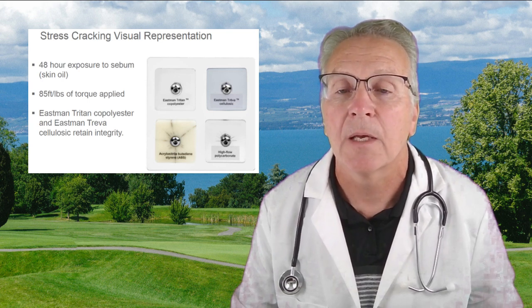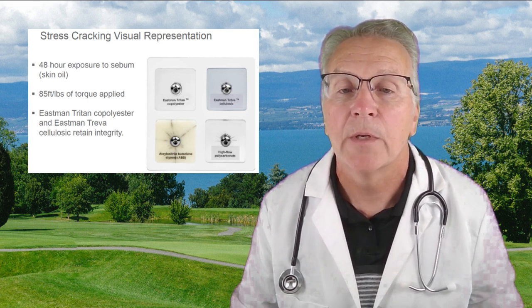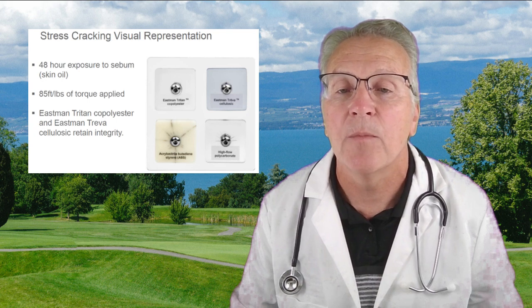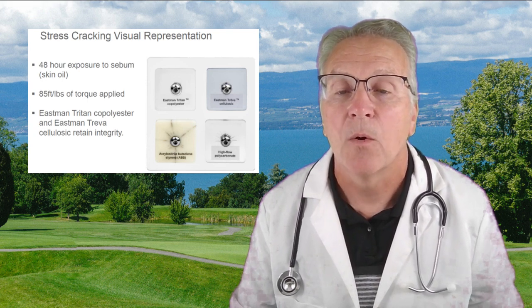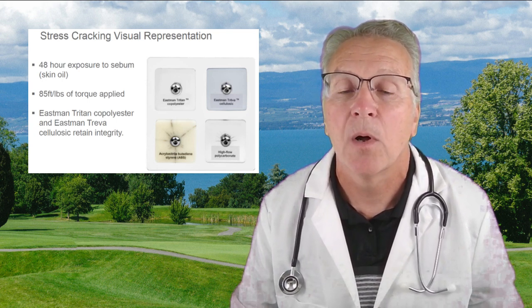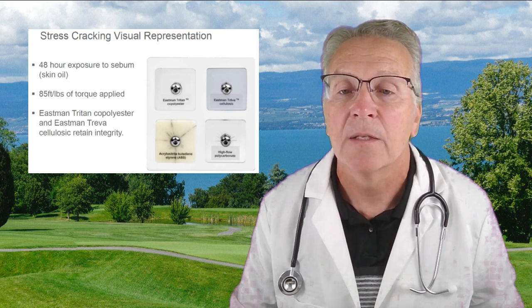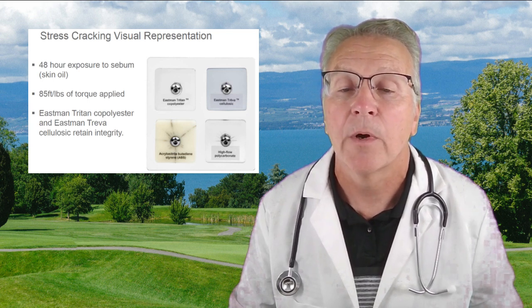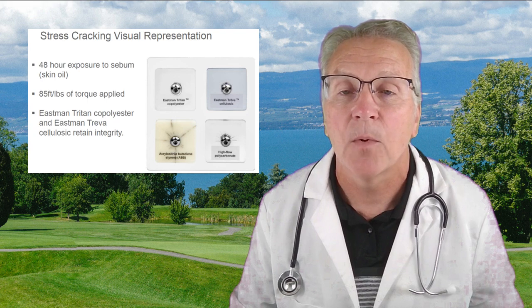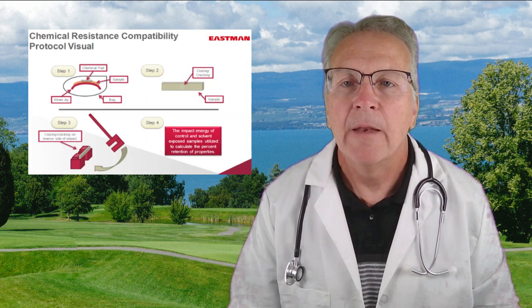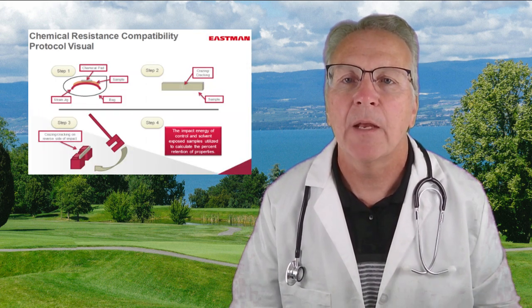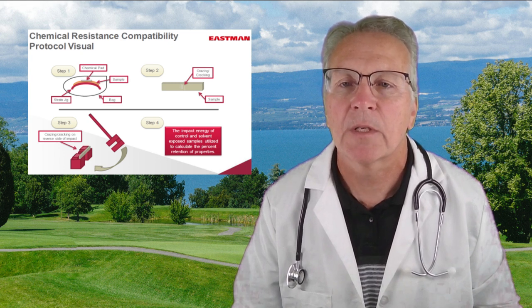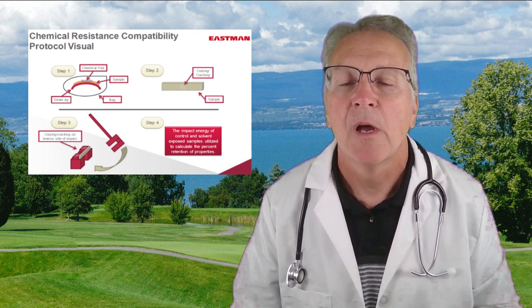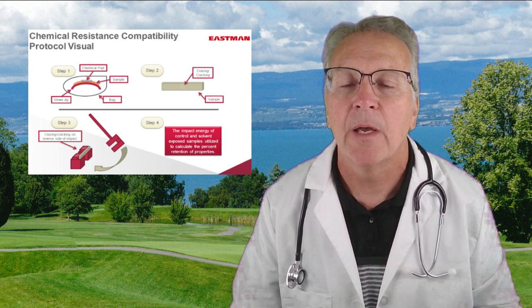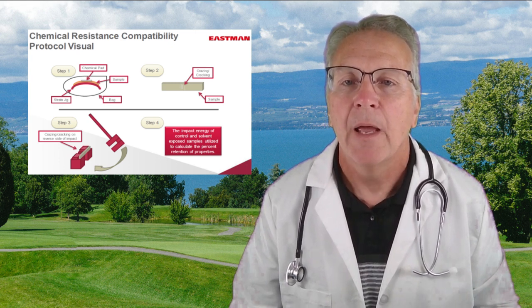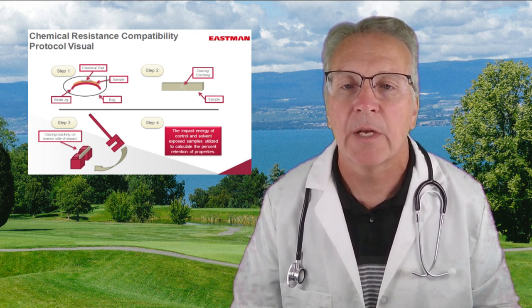better than ABS and polycarbonate using a known test torque in the presence of sebum or skin oil, because the oil cracks the ABS and polycarbonate in 2 days, since the given force and chemical creates brittle failure in these samples. An ESCR fixture schematic is shown on your screen, in which the sample is bent over the fixture, causing a known stress and strain, and chemicals are applied and impact strength retention is tested.